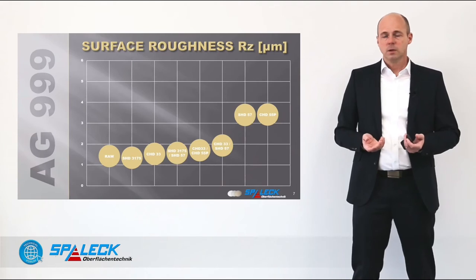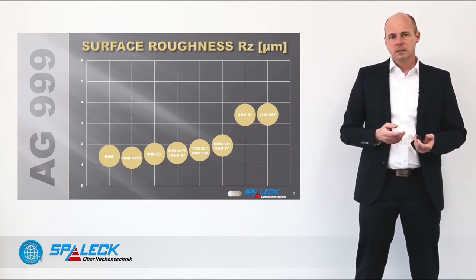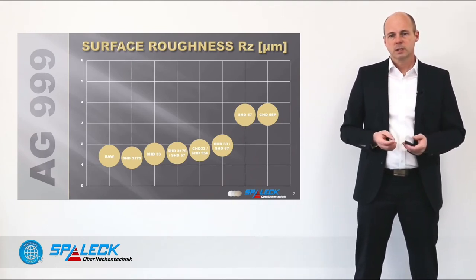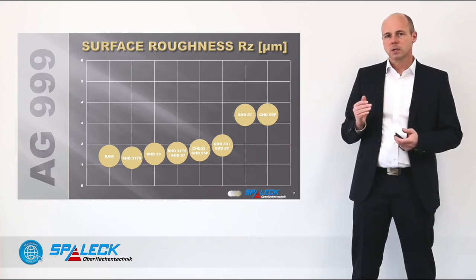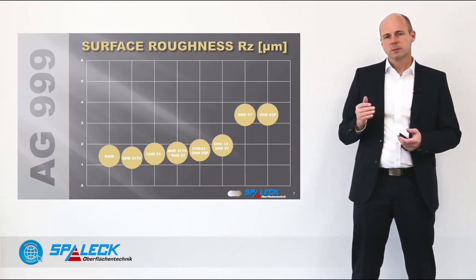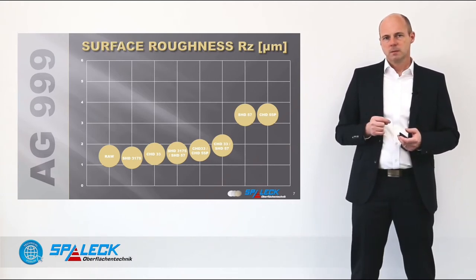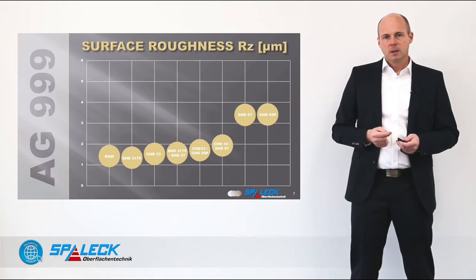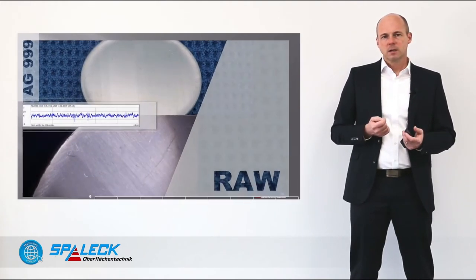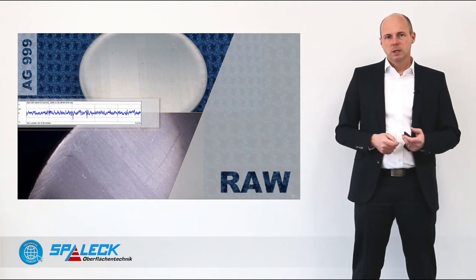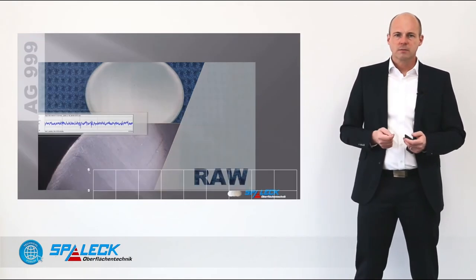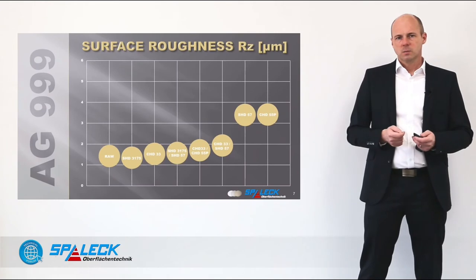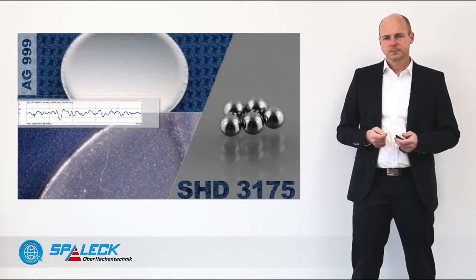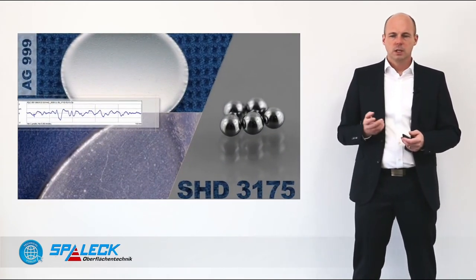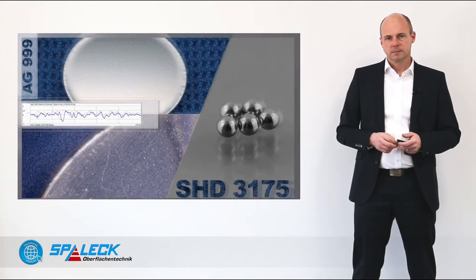After the sterling silver, we also analyzed the fine silver, which is a softer material. Here you see a similar order of different surface roughnesses, again as a function of the weight and the geometry. To treat fine silver, the raw material, with satellites is a bit too rough, so typically you start with stainless steel balls, which here give the desired result.